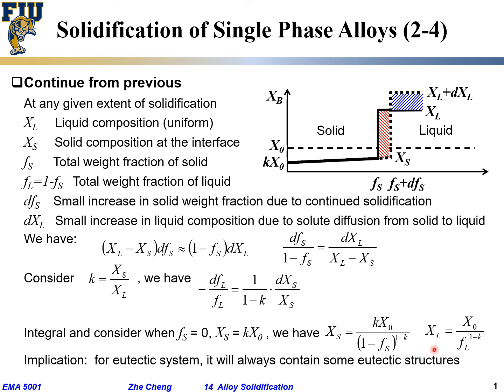What happens to this XL? It will keep increasing until it reaches what? Until it reaches so-called eutectic composition. And at that moment, the liquid composition can no longer increase. And then at that moment, the liquid will change by eutectic reaction, liquid into solid. Okay? So that's kind of okay. Why for such a system? If it's a eutectic system, it will always reach eutectic temperature, reach eutectic composition. Okay?